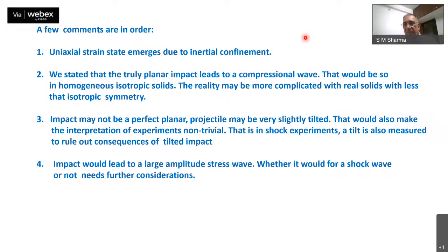Also, when you design an experiment, it is okay mathematically to make an assumption that an impact is planar. It just comes and makes an impact only parallel to the YZ direction. In reality, it doesn't happen. Any object, any projectile that you may design, when it comes flying, it may have a slight tilt, and depending on the tilt of the projectile that is coming and hitting, it may alter the results. So therefore, shockwave experiments require that the tilt be kept very low.